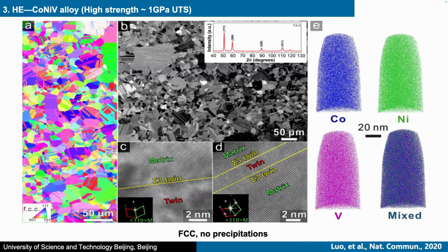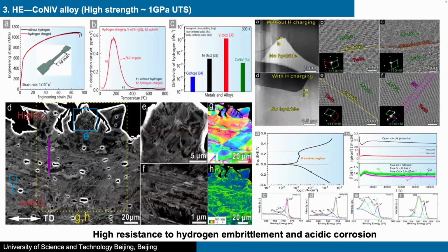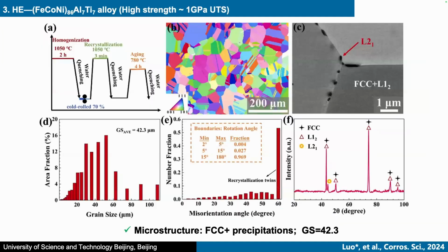It is the cobalt, nickel, and vanadium alloy. It's also pure FCC, no precipitations. And we did a similar experiment. And we also found that the hydrogen embrittlement resistance is very good. And also, if we charge it for a long time, no hydride formation, which means it's very stable under the hydrogen environment. And also, an additional property is this alloy has very good acidic corrosion resistance.